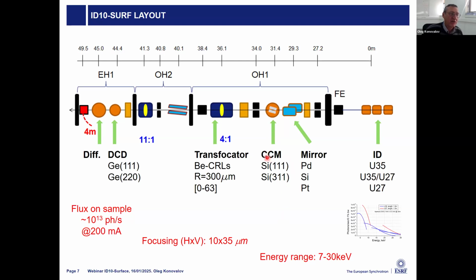And there is the possibility to work either with silicon 111 channel cut or with silicon 311. So again, this depends on the energy which we want to use, and also on the bandwidth after the monochromator. And our typical range of measurements where we can work is between 7 and 30 kilo electron volts.